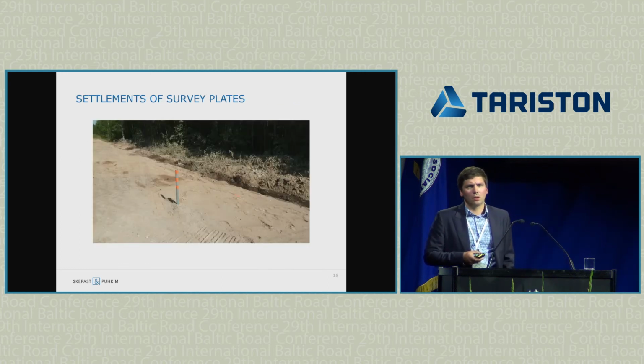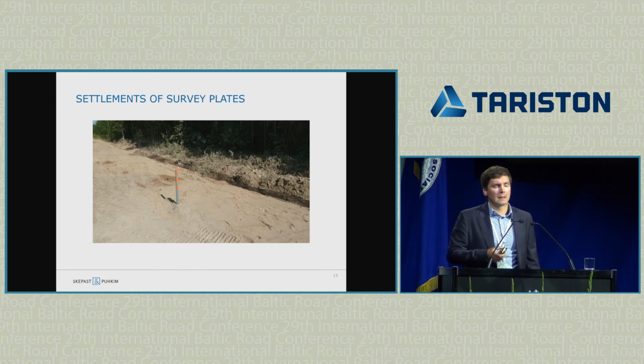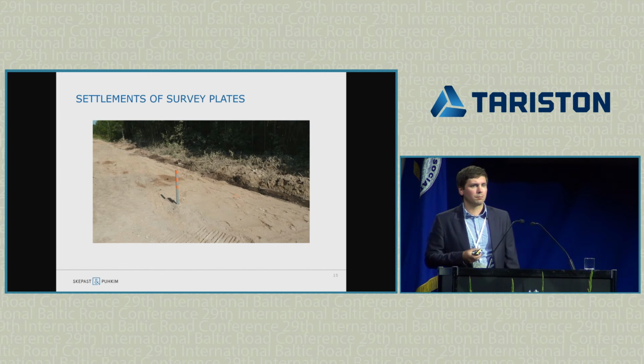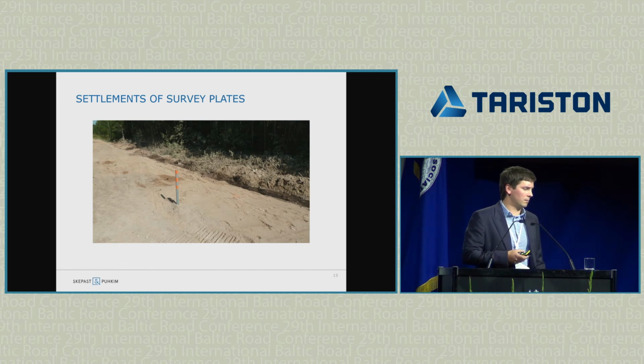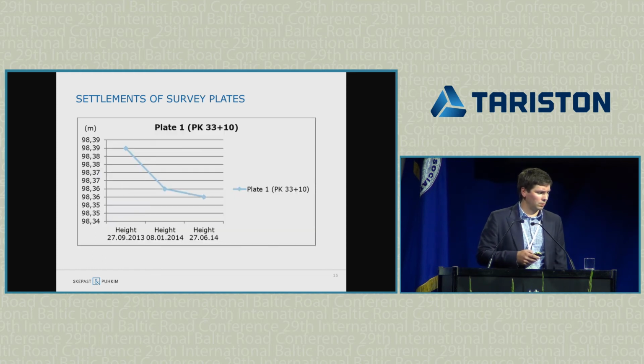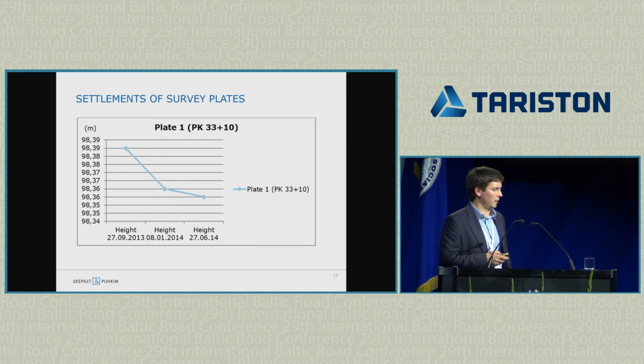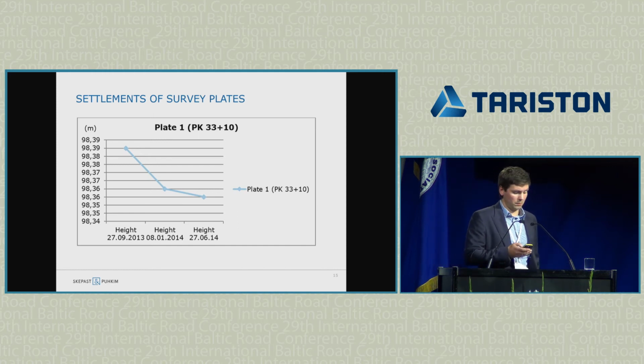Then we measured how the stabilized layer is settling. For that, we installed 5 metal plates on top of the layer, and we put 1 stick into it to measure the height in different places. And we found out that in about 1 year, the settlement was some 4 centimeters, which is okay, also based on experience in Finland, as this was done on an existing road. When it's done on a completely new road, of course, the settlement is bigger. The numbers are bigger.